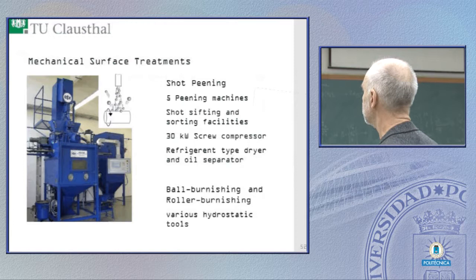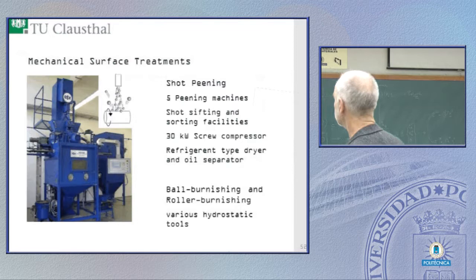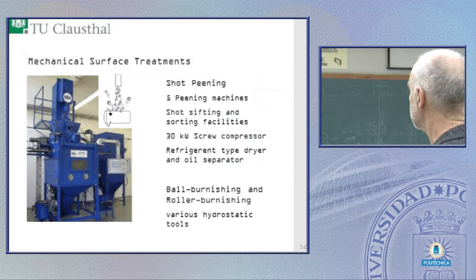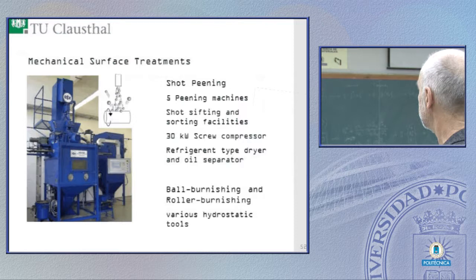and the fatigue performance. I must apologize for the quality of the slide, but I think it comes from the different versions. Fatigue performance, the experiments were done with R equals minus 1. This is swaged and annealed, and this is only annealed, and you see the same effect that we saw before, the increase of the fatigue properties.